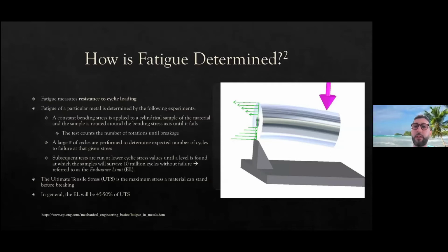I've put an illustration up here, which is a picture of a rod. Basically, you apply constant bending stress to a cylindrical sample of the material, and you rotate it about that stress axis, and you count the number of rotations until it breaks. You do that repetitively for a large number of cycles, and then you can determine the expected number of cycles to failure at a given stress. They run all these different tests. You can run subsequent tests at lower cyclic stress values until you find the stress at which a sample will survive 10 million cycles, and that's referred to as the endurance limit.